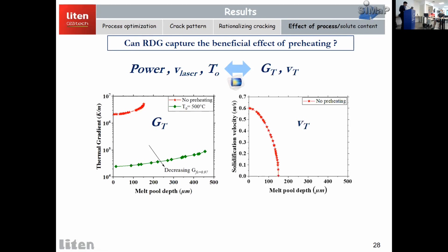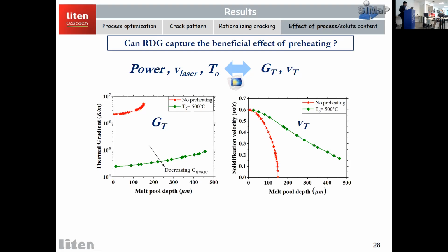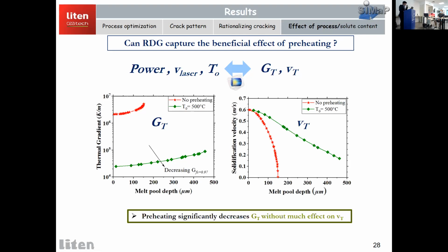But let's see what solidification velocities give. For no preheating, we have a decrease as a function of melt pool. But when we introduce the 500 degrees Celsius of preheating, our solidification velocity is not that much affected. The magnitude is not changing, although there is a slight difference since melt pool dimensions might change due to preheating. So the thermal gradients are hugely affected without much effect on solidification velocities.